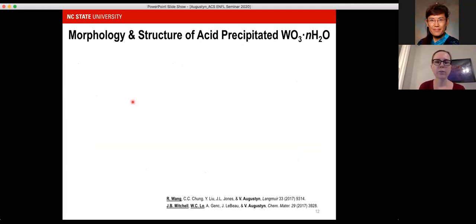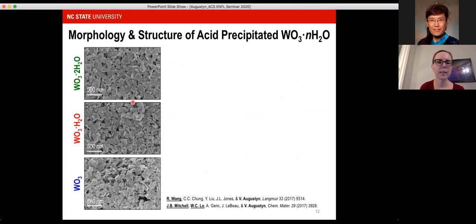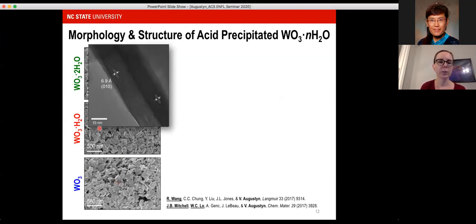Here's a little bit about the morphology and structure of these materials. If we synthesize it using the acid precipitation route, we get these platelets. The dehydration process does not change the morphology, does not really change the surface area. So this is important when we look for structure-property relationships, since electrochemical kinetics will always be affected by the surface area. One of the things that's really important when working with hydrated materials is to consider their vacuum stability in addition to the thermal stability.